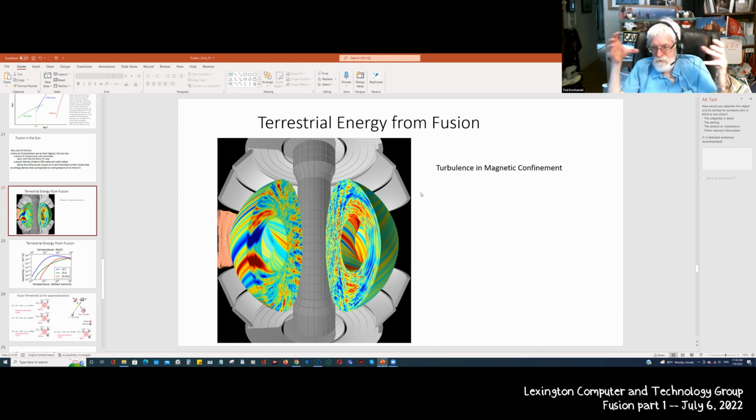There's incidental damage to the confinement of the core in the reactor vessel, and you can accommodate that by keeping that relatively hot. And so while the neutrons are banging into the iron atoms and stuff like that in the steel, you can anneal it continuously. Essentially, the neutrons are much less energetic as well by the time they get to the actual reactor vessel in a fission reactor.